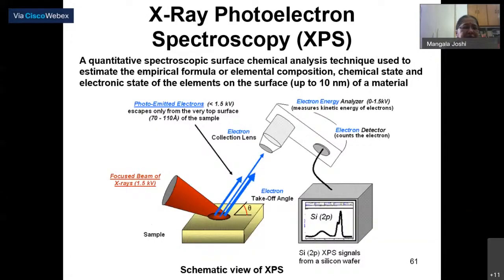XPS is a quantitative spectroscopic surface chemical analysis technique, and it helps to estimate the elemental composition, chemical state and electronic state of elements on the surface, up to 10 nm, of a material. Here again you have a focused beam of X-rays, and then the electrons are ejected out. The energy of the electrons which are ejected depends on what the material is, so the binding energy is caught. I'm not going into detail now because time is short, but basically the ejection depends on the nature of the sample.